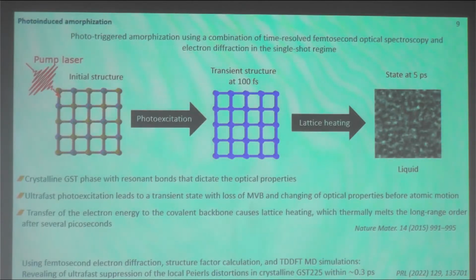Also, in this publication, it was shown that by using femtosecond electron diffraction and structure factor calculation and some simulation, it was revealed that it is also possible to suppress local Peierls distortions. You know that this system, cubic GST, is highly distorted, also posing so-called Peierls distortion, and then it's possible to suppress it in crystalline GST within 0.3 picosecond. So just to change from one bonding state to another bonding state.